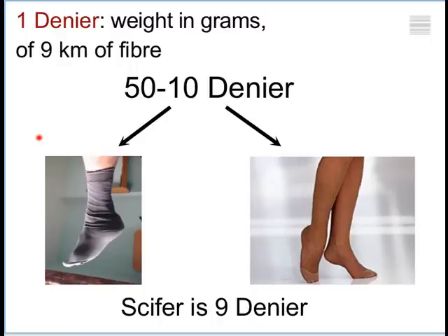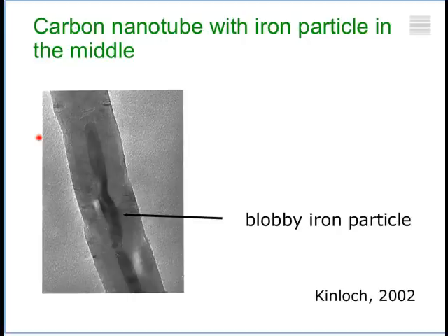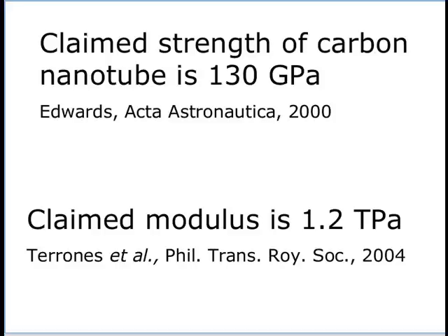the semiconductor. And these lessons that we have learned so far have mostly been forgotten, that if you try to produce strength by introducing perfection, then your material will be very sensitive to the size of your sample. So you must have heard about carbon nanotubes. There are more papers published on carbon nanotubes than ever published on steel. And the reason is that these tubes of carbon have an incredibly high modulus, and this is the modulus, 1.2 terapascals. So this is 6 times the modulus of iron, and they have an incredibly high strength, 130 gigapascals.